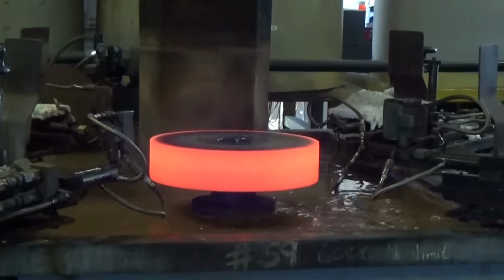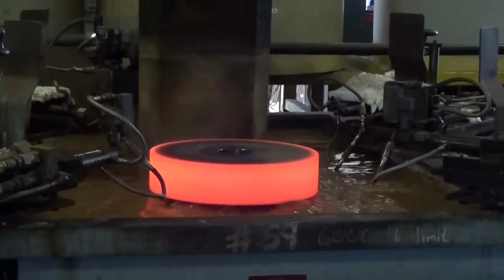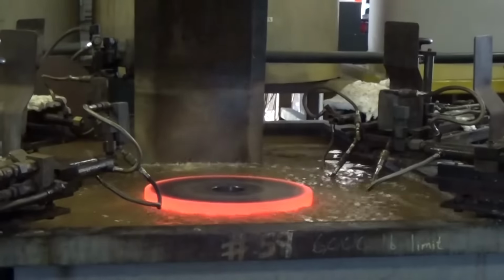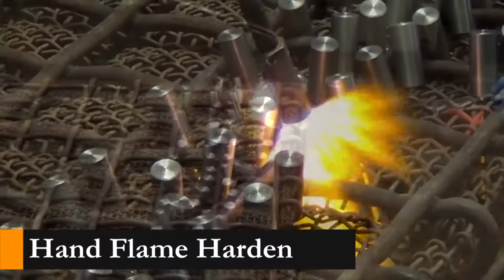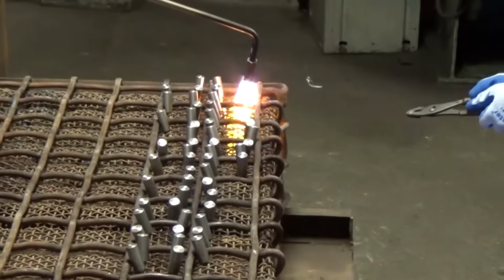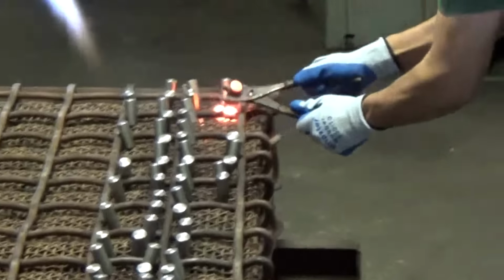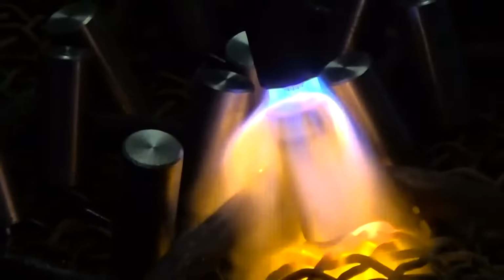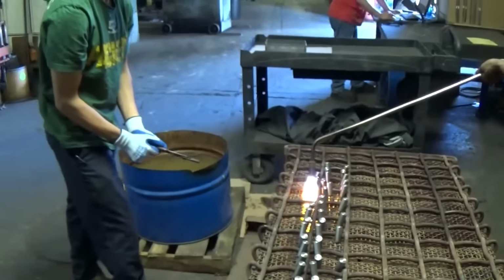Once the part has been heated to the desired temperature, it is lowered into a quench bath, resulting in a case that is hard on the outside but has a ductile core. Flame hardening can also be done with a hand torch. In this case, only the top face of these pins will be hardened, and the operators judge the proper temperature by eyesight. This skill comes with experience.